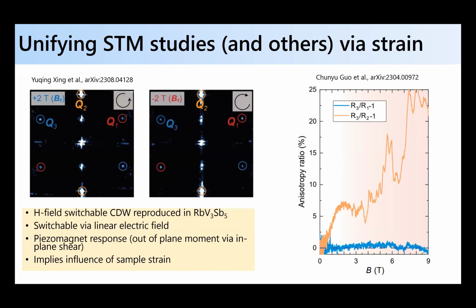Okay, but I will say something that's been interesting and very recent. Vidya has some recent beautiful work looking at the rubidium compound, where they were able to reproduce this magnetic field switchable charge density wave state from the original report from Hasan's group at Princeton. But they also were able to resolve a piezomagnetic response in the system. A key observation is they can also switch the chirality apparent on the surface of the CDW by the application of a linear electric field, meaning linearly polarized light can switch it.